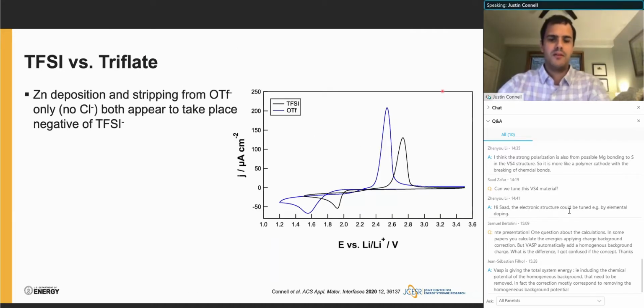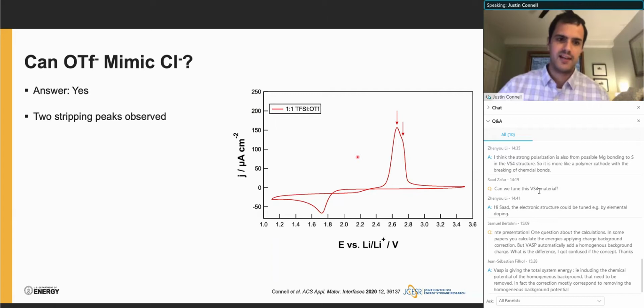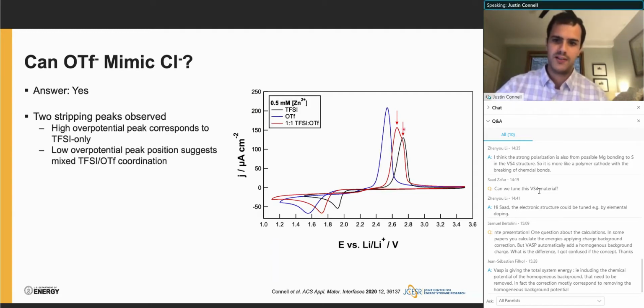And so if we compare the plating and stripping of just the 2 constituent electrolytes, so TFSI only in the black and triflate only in the blue, we see that the whole redox event appears to shift to lower overpotential, consistent with the higher association strength of the triflate anion. And so, to answer this question, can triflate be used to mimic chloride? We see the answer is actually yes. In direct analogy to the mixed TFSI chloride system, we see 2 distinct oxidation features in the mixed TFSI triflate system. And if we overlay the voltammograms I just showed, we see that this first oxidation event overlaps exactly with that of the TFSI only system.